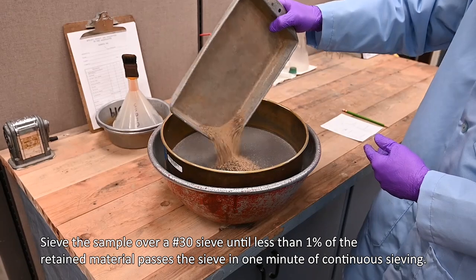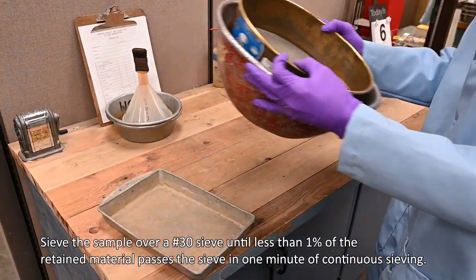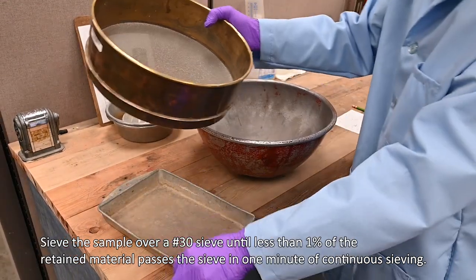Sieve the sample over a number 30 sieve until less than 1% of the retained material passes the sieve in 1 minute of continuous sieving.